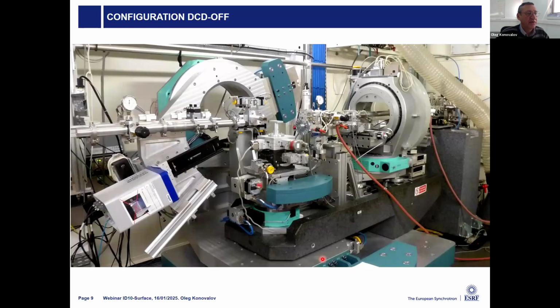And this is a view of the diffractometer in the way when we don't use the DCD. So then the beam just goes through the flight tube. We have a monitoring system, slits, and an attenuator wheel. The attenuator is used to change the intensity of the beam on the sample. On one side to protect it, but also to have a beam which is digestible for the detector, so that the detector works in a linear regime and doesn't saturate, so that we can measure.